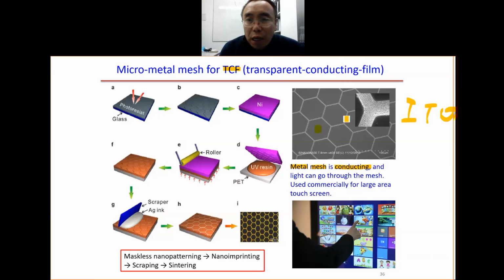So how to make this metal mesh structure? Here is the process. First, we do photolithography to pattern the photoresist. Then we do nickel electroplating to copy the mold onto the nickel. Then we put the nickel mold onto this UV curable resist. Again, the substrate is PET. Then you do the roller imprint.